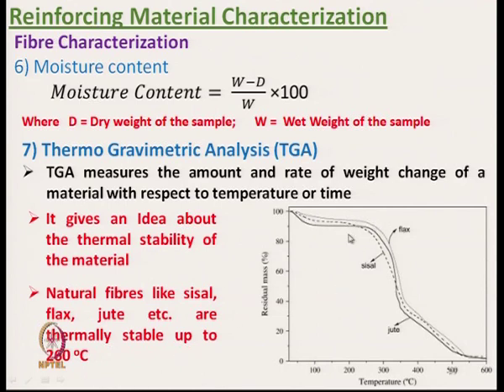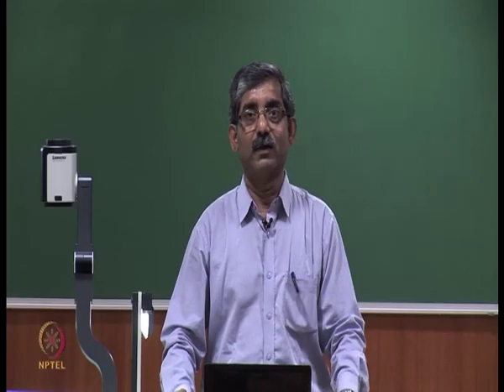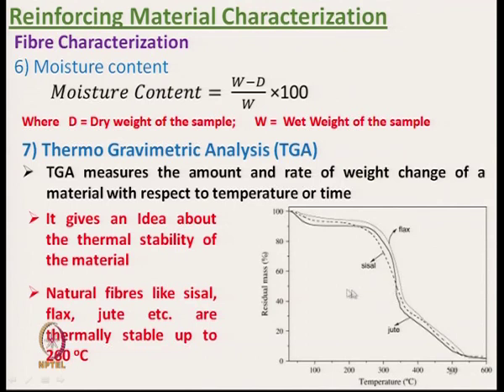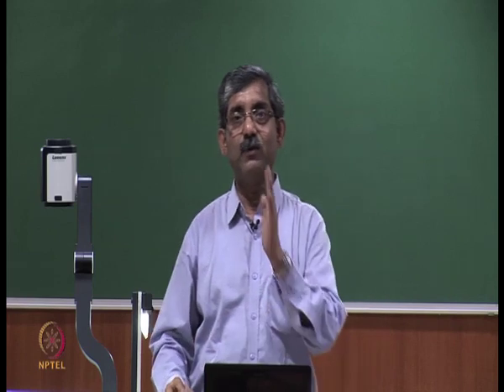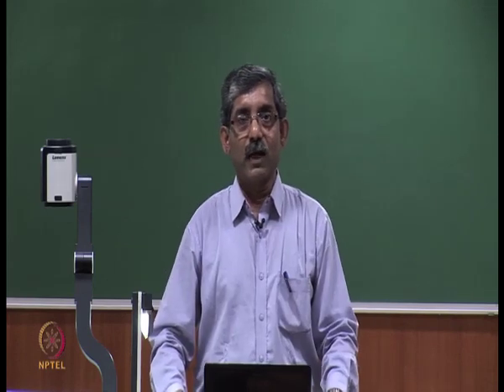Celsius, and after that it is not stable anymore. Beyond that temperature, it starts decomposition and then the residual mass drops gradually. It is steeply there will be a drop, okay. So, that shows the TGA testing. Okay. So, we can come to know with this curve how stable the material is up to what temperature. We will stop here,